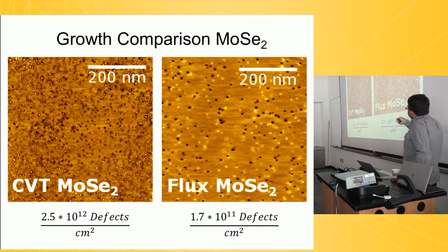And so what I can do is I can just look at the total number of atoms in this image. I can count the total number of defects in this image, and I make a defect count. Very simple. And for this particular material, the defect count is about 2.5 times 10 to the 12 defects per square centimeter. In other words, between 0.1 and 1% of sites are defects, which is an absolutely enormous number. So this is now with our improved technique, the flux technique. We do the same thing. We can get a defect concentration that's about an order of magnitude better. So we can get down to 1.7 times 10 to the 11.